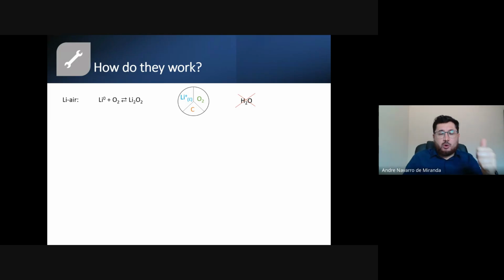We cannot have water because we are working with metal lithium. Metallic lithium is really reactive to water, so we cannot have water in the system. We also cannot have CO2 in the system because there is a tendency to form lithium carbonate that's really stable and does not decompose. So it's another problem. We also cannot work with high currents because it tends to form lithium carbonate, Li2CO3. So it's really dangerous to the battery as well. So these are some challenges that we have to overcome to use this technology.